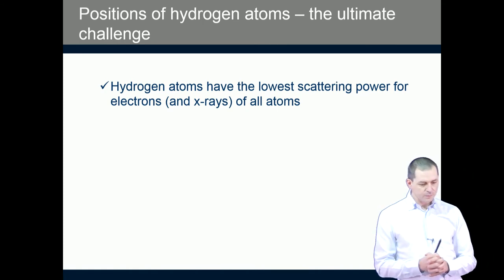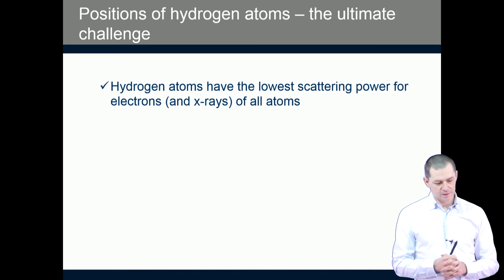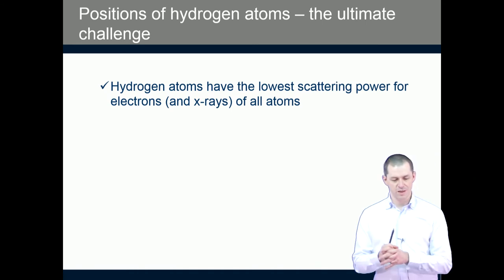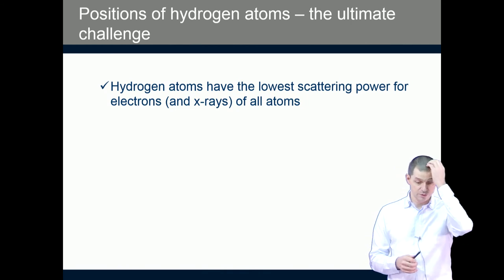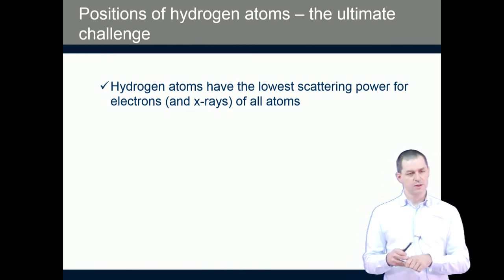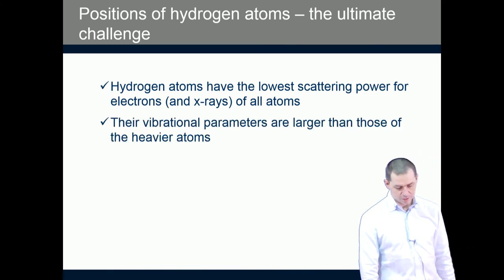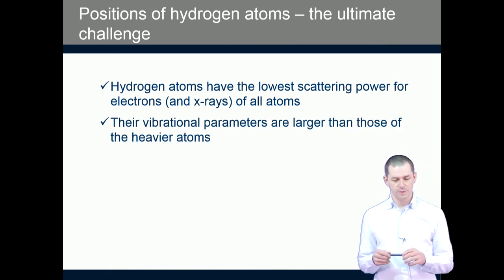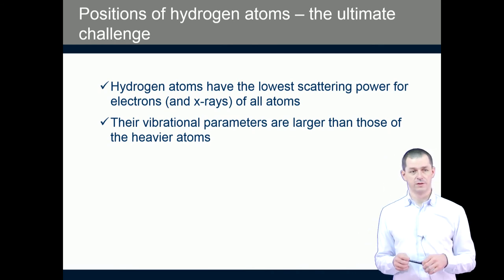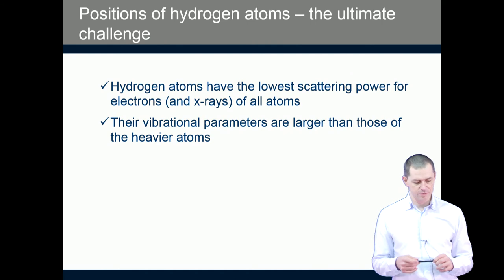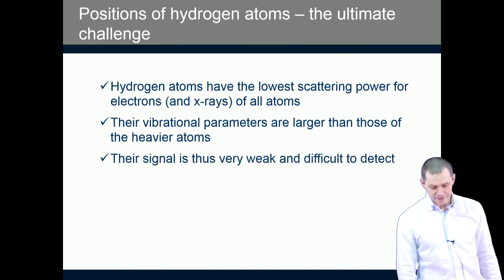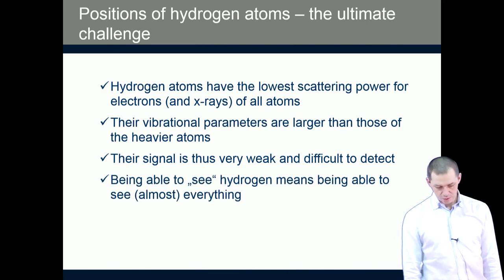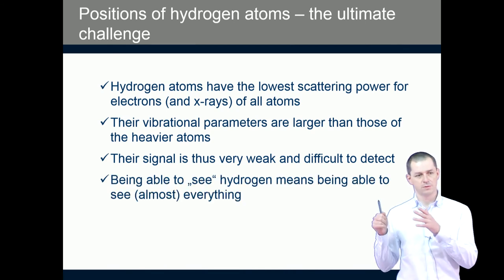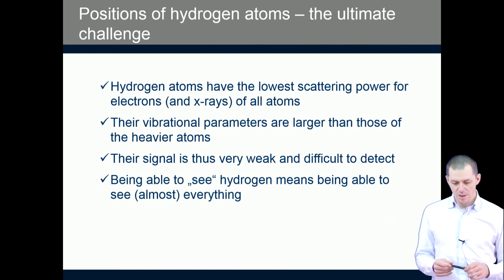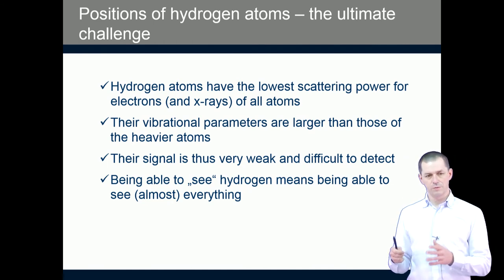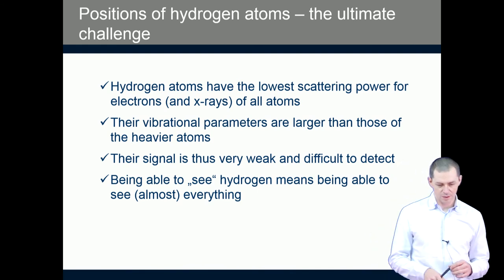And in this respect, finding and locating position of hydrogen atoms is the ultimate challenge, because hydrogen atoms really have the lowest scattering power for both electrons and X-rays, and in addition they have vibrational parameters that are larger than the vibrational parameters of other atoms in the structure, and therefore their signal is very weak and difficult to detect. So in a sense, if we can show that our method allows location of hydrogen atoms, then it's a sort of a proof of the sensitivity and reliability of the method.